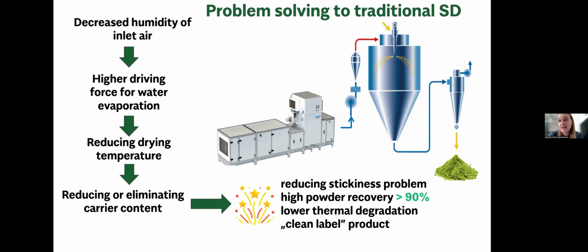So what actually air dehumidification can solve the problems that we encounter with traditional spray drying. By decreasing air humidity of inlet air, we are ensuring higher driving force for water evaporation. In consequence, we can reduce drying temperature, and then we can reduce carrier content and/or eliminate it completely, which I will show you in a few of our case studies.